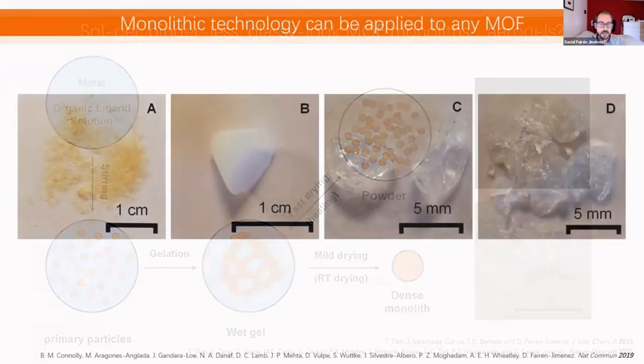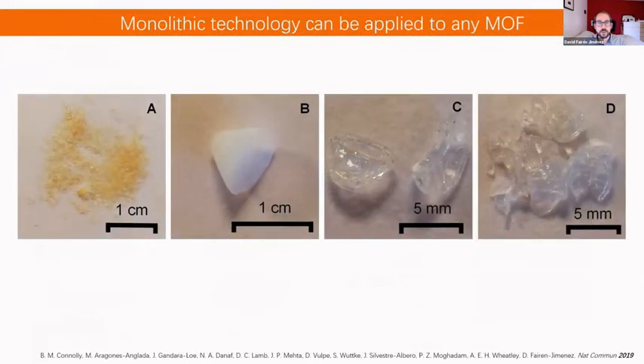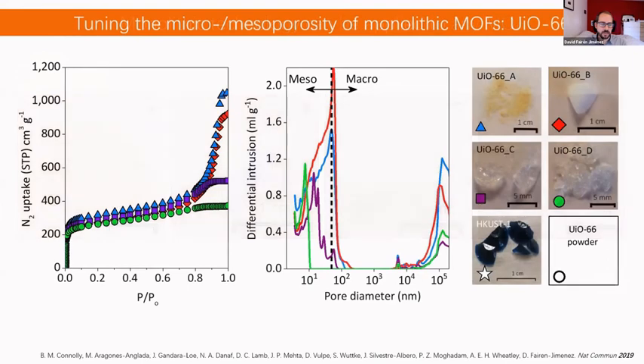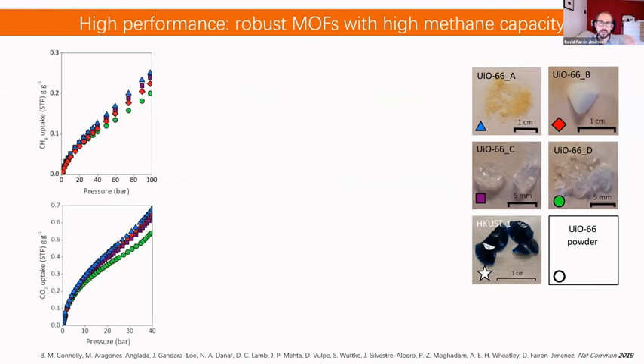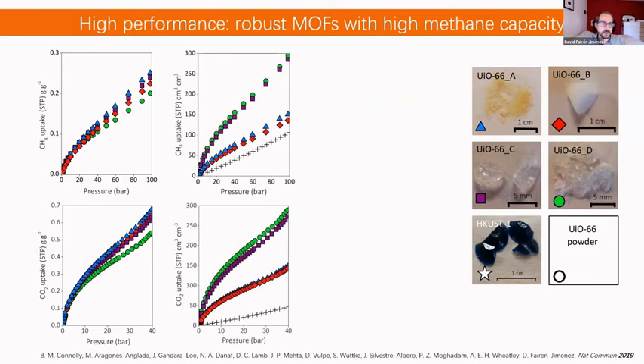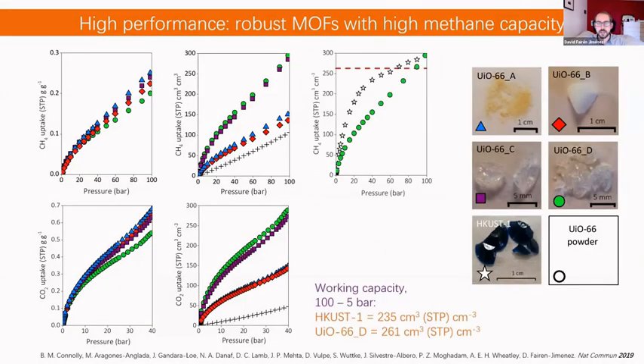Just a very few slides. We can basically apply this monolithic technology to any MOF that we have been trying to work with. Okay, and we have different profiles with different micro and mesoporosity, which also means we can translate this into different performance applications, okay? I don't want to put too much attention on these adsorption capacities, but basically, if we transform gravimetric capacity into volumetric capacity, we multiply by the density of the MOFs. If the MOF has high density, the volumetric capacity is going to be very high. If the density is very low, the volumetric capacity will also be very low, okay? At the end of the day, really interesting materials.